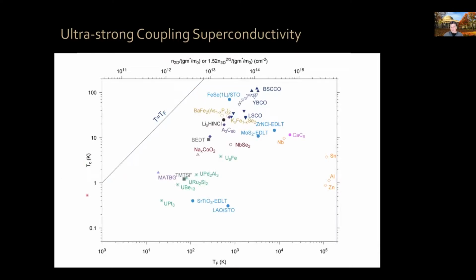In fact, when physicists compare how strong are superconductors, typically one looks at what is the value of the critical temperature versus the Fermi temperature, which is like the density of electrons, okay? Now you can have different limits in 3D or in 2D, okay? And basically in this diagram, conventional superconductors tend to be near this corner. For example, aluminum has a TC of 1 Kelvin and a Fermi temperature of 100,000 Kelvin, okay? Given how many electrons aluminum has, it superconducts very modestly. As we go towards this diagonal, you find more and more unconventional type of superconductors. In fact, this purple band contains the cuprates, the pnictides, organics, the heavy fermions, pretty much all the unconventional superconductors that we know.